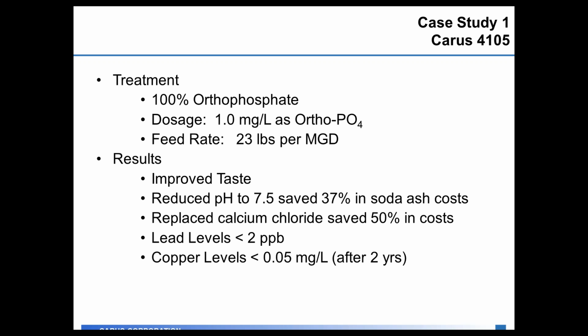When they made this change, they also looked at doing two other treatment process changes in the plant itself. So they reduced the pH from 8.4 down to 7.5, reducing the amount of soda ash that they were feeding to the water, and that saved them 37% in operating costs.